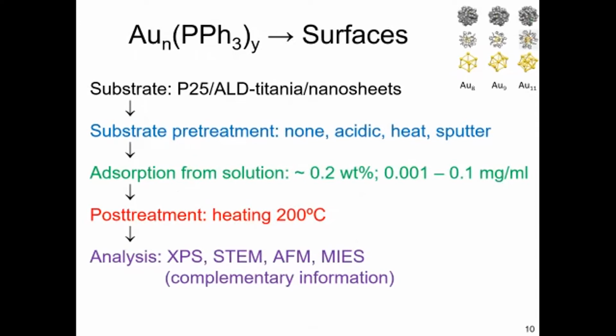We heat it, for example to 200 degrees, to remove the ligands, and we study by different techniques what happens to the size and to the electronic structure of this cluster. Our main goal is to have this gold cluster at the end as a naked gold cluster, with the ligands removed and easy access, but without any aggregation of the cluster.